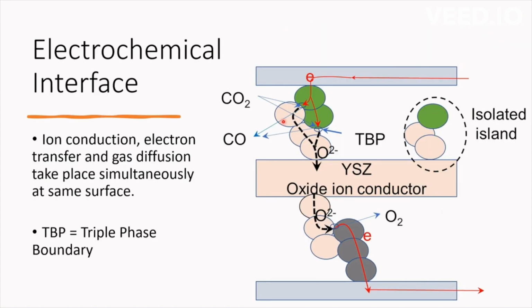For working of the cell, there should be a triple phase boundary, that means gas diffusion, electron transfer and ion transfer should take place simultaneously at the same surface. To achieve this, the electrode should be porous for gas diffusion and it should be ionic as well as electronic conducting. You can see here in these blue circles, when CO2 gas diffuses, with the help of electricity it is reduced to CO and generates oxygen ion, which is transferred by the ion conducting material from cathode to anode, where it gets oxidized and generates oxygen gas. So we are tracking the cathode surface to investigate the mechanistic insight of CO2 electrolysis.